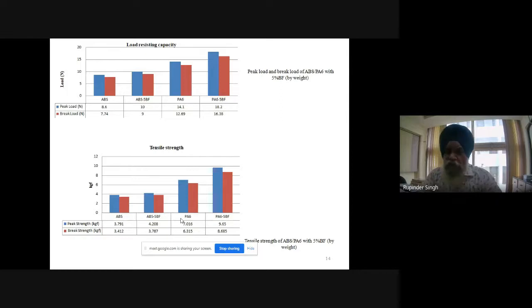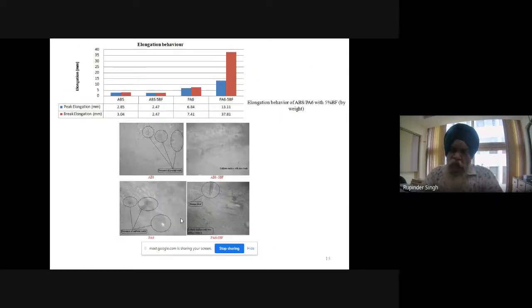Then we try to see some of the mechanical properties like load, elongation, and we try to correlate it with the porosity level. This is really important because once you have a different level of porosity, it will be affecting your epsilon r, right? Because your permittivity, that is responsible for getting a charge with respect to the capacity of the air, is really dependent on the porosity. So for the typical sensor application, this has to be really controlled, right?